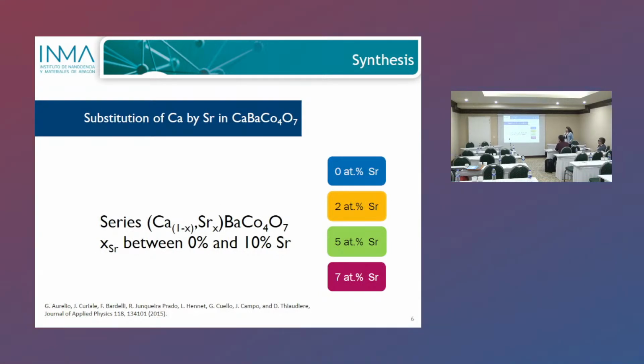What I will be showing you today is what happens when you start playing with this 2+ cation at this site of the structure. So we replaced calcium by strontium, and we prepared a series of samples. The highest level we could achieve for pure samples was 7 atomic percent strontium, because if you go higher, you start to segregate strontium. So we did very careful measurements to check that we were putting strontium really at that site, and that the samples were pure.